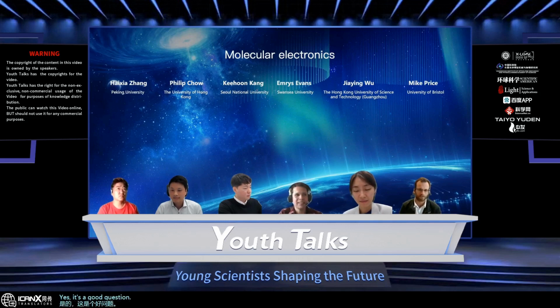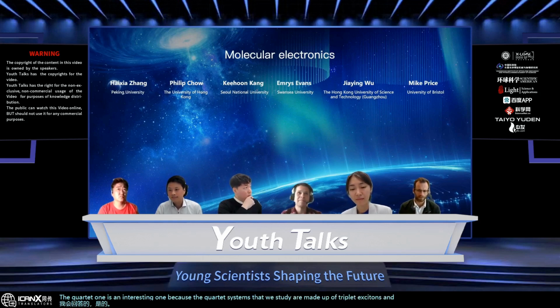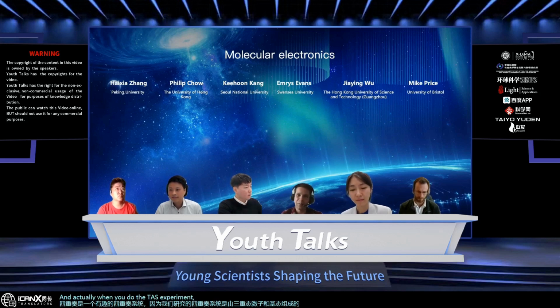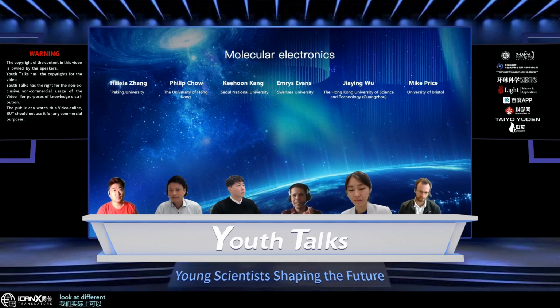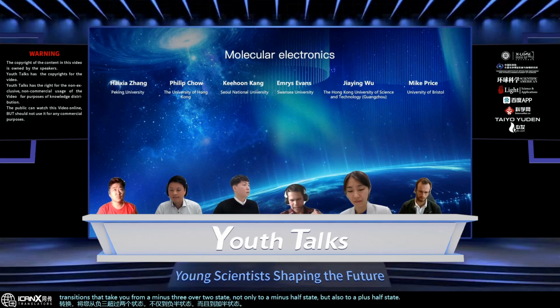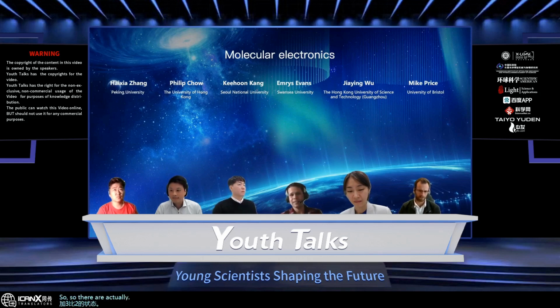Yeah, it's a good question. The quartet one is an interesting one, because the quartet systems that we study are made up of triplet excitons and ground state radicals. And actually, when you do the TAS experiment, you can't distinguish a quartet state like that from a triplet exciton itself. So what you really need is to do magnetic resonance experiments. With electron paramagnetic resonance experiments, we can look at different transitions within the spin sublevels. For example, a quartet state has transitions that take you from a -3/2 state, not only to a -1/2 state, but also to a +1/2 state, and to a +3/2 state. So there are fingerprints in the electron paramagnetic resonance that can tell you whether you've got a quartet state in there.